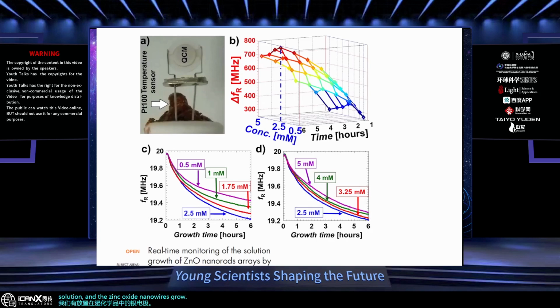So as long as they grow, the resonant frequency of the microbalance will be reduced because of the increased mass of the electrodes, and that is how we can monitor. But more in general, you can use the same approach, but it depends on the type of nanowires you want to grow and to monitor, and also on the type of substrate. I'm not sure if this answers your question.